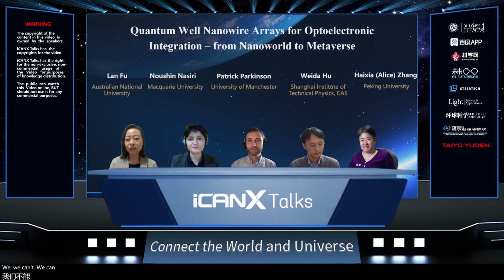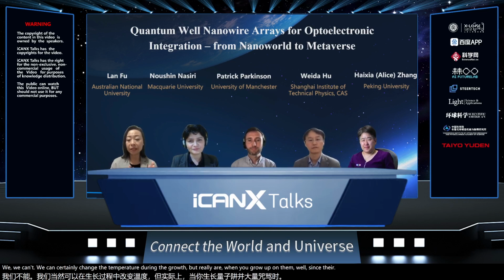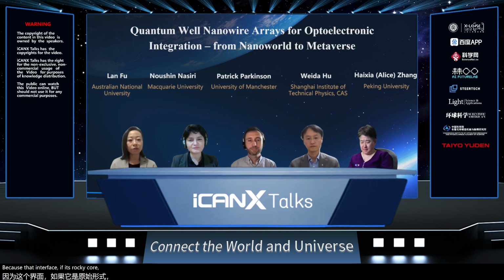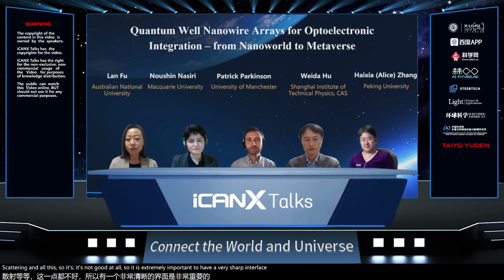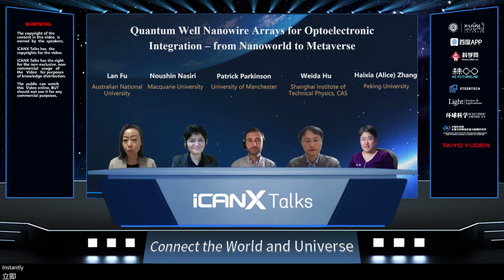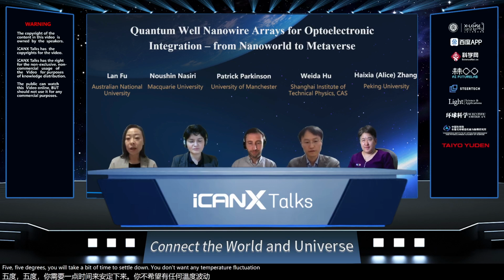We can certainly change the temperature during the growth, but when you grow quantum wells, the interface you create is very important, because if that interface is rough, it causes a lot of scattering and all this, so it's not good at all. So it's extremely important to have a very sharp interface. So during that growth, for our structure, we don't stop, because changing temperature is not instant. You have to wait. You change 5 degrees, it will take a little bit of time to settle down. You don't want any temperature fluctuation during the growth of the very thin layer.